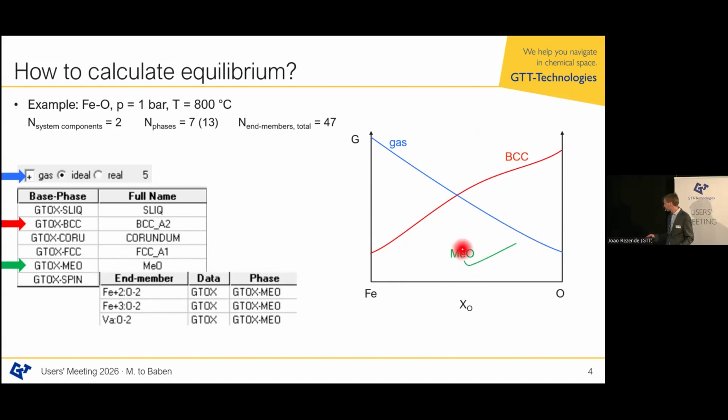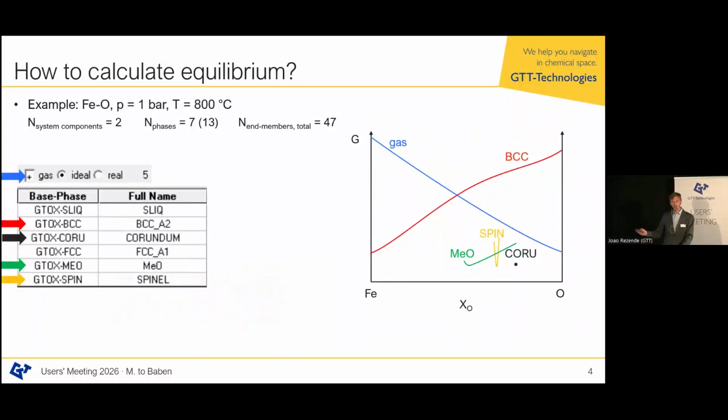It is going from the 1-to-1 stoichiometry here to a 2-to-3 stoichiometry that you can get by charge balancing the 2 lower end members here. And then we can also add the other 2 solution phases, the spinel phase, which is around the Fe3O4 composition range, and the hematite, which is at the Fe2O3 composition, and that's actually modeled only as a point compound, and this is why I've only put this here as 1 point.